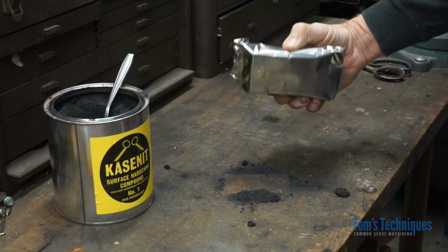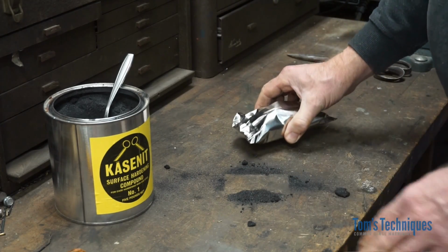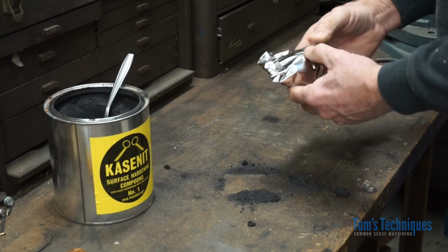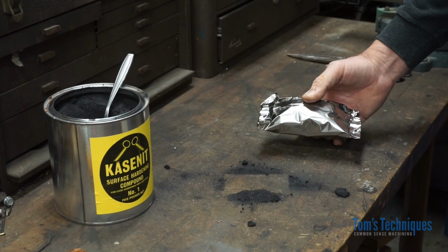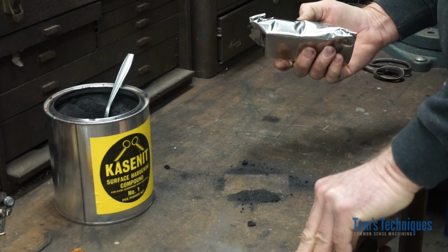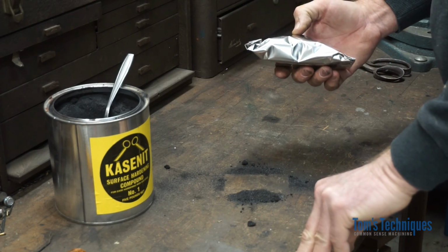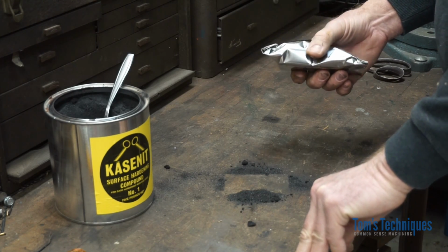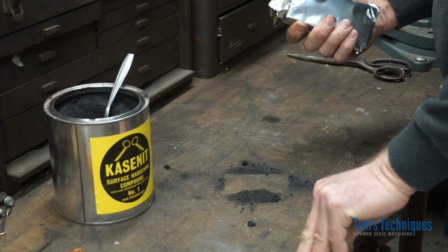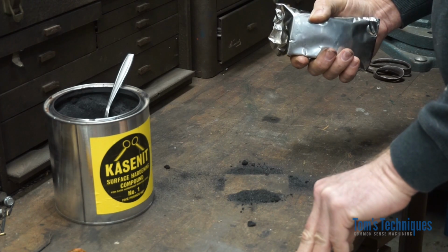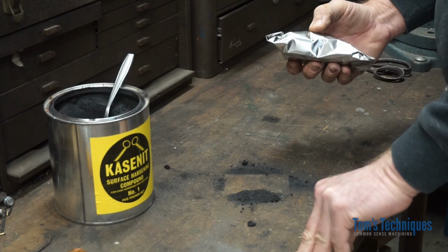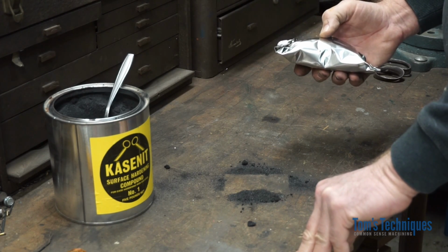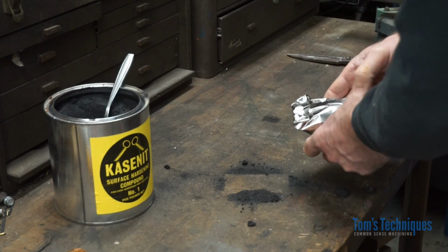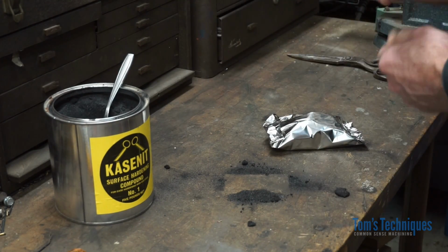Okay, now we've got to heat this whole thing up to between 1500 and 1600 degrees Fahrenheit and let it soak for a while. The longer you let it go, the deeper the carbon layer is going to get. So I like to keep it up to a red heat for about an hour. That'll give us a couple thousandths thickness of hardness on the parts, which will greatly increase the durability of them.